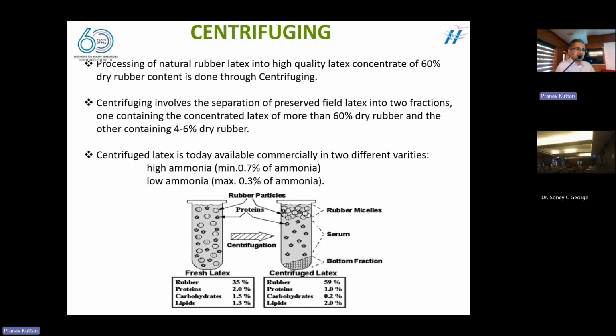So when you are centrifuging, as I said, the water is separated and the latex is concentrated to a maximum percentage of 60% by this process. So the remaining 40% will be water. Other than that, the concentration will be much more difficult. So this concentrated latex is used for making products from latex alone. So centrifuging separates the water, separates the rubber, 60% of rubber, and the remaining 4 to 5% of dry rubber goes along with the centrifugate, the remaining solution of serum, which is called skim latex. It contains 4 to 5% of latex.